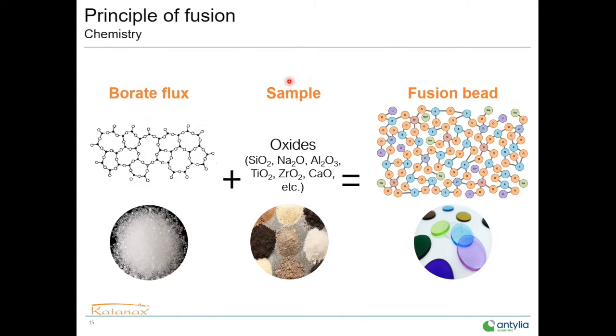When we melt this flux and mix it with a sample oxide, typically we will see together that the sample needs a specific requirement to be compatible with this flux. So we will talk about oxides, different pure oxides or mixtures of them. You can have an idea of the different powders here. Both mixed together at high temperature will give this kind of complex molecular distribution, where the elements of the sample will enter the glass matrix to end up with a solid glass bead of specific composition. It's possible to obtain a glass bead, but it's also possible, we will see it today during the manipulation, to form this complex glass matrix and pour it into a solution to create a liquid sample for ICP analysis, instead of a solid sample for XRF.